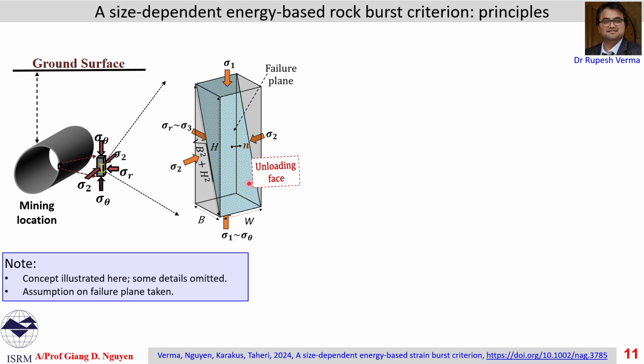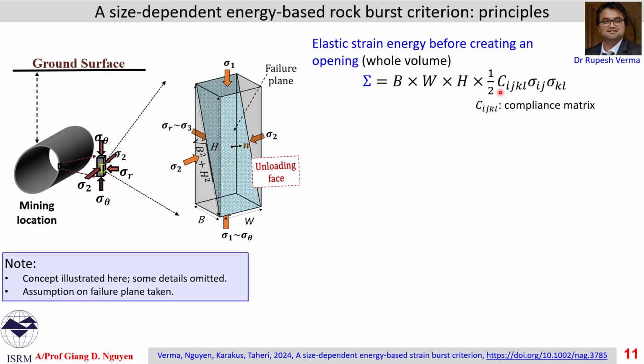So if we consider this kind of prismatic volume element with width W, depth B, height H, is given under three principal stresses, sigma 1, sigma 2, sigma 3. We can work out the elastic strain energy stored in this volume element before the release of stress in one direction. And as you can see here, it is scaling with the volume of the element, and 1/2 C_ijkl sigma_ij sigma_kl.